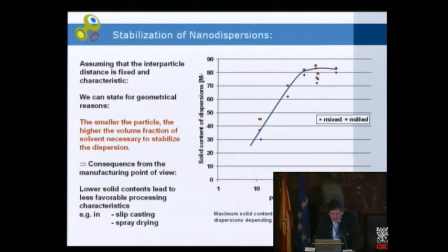Paul will give you more details on that. I will shorten that a little bit. But just one early experience when we started with the casting of far submicron nanopowders by traditional pressureless casting. In about 25 years, we developed a lot of very well studied recipes on how to achieve a stable suspension, but also a very high content of solid.